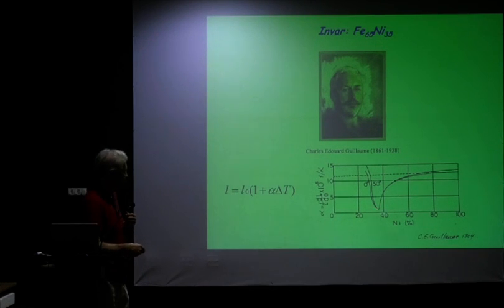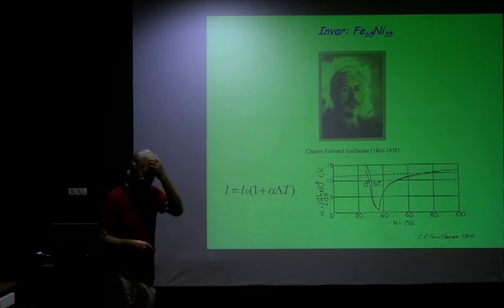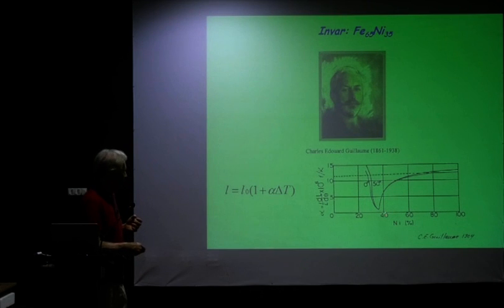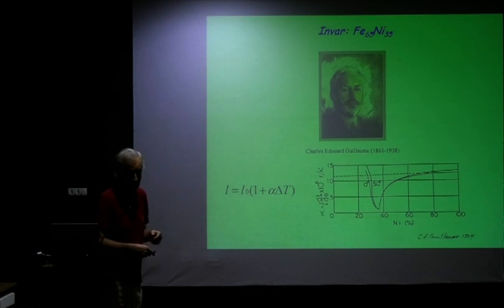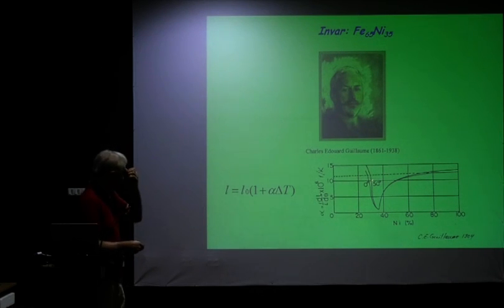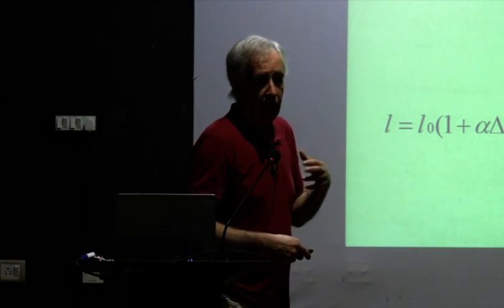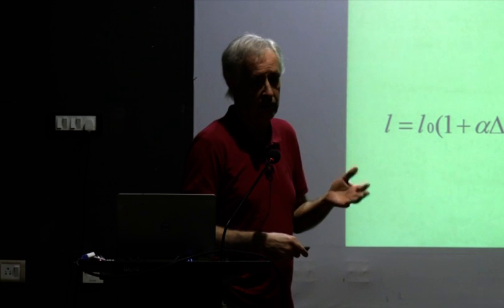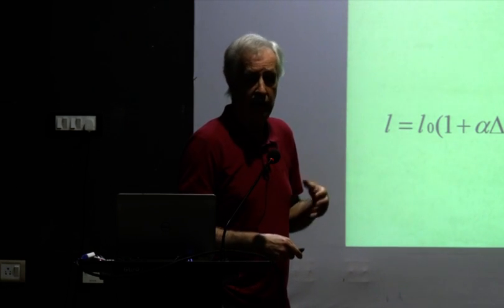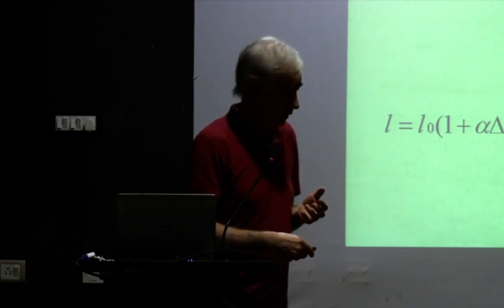This is the composition, this one over here. This is the thermal expansion coefficient, this is the nickel concentration of iron-nickel. So at about 65% iron, 35% nickel, they came to this composition. You see he measured this at 0 degrees and at 50 degrees centigrade. Those were the temperatures that were available or controllable. He found this material, and they named it Invar. It became a trademark, and in 1920 he got the Nobel Prize for this.